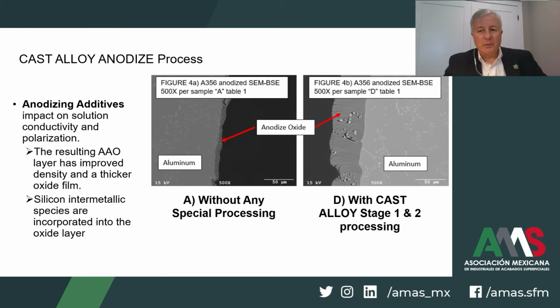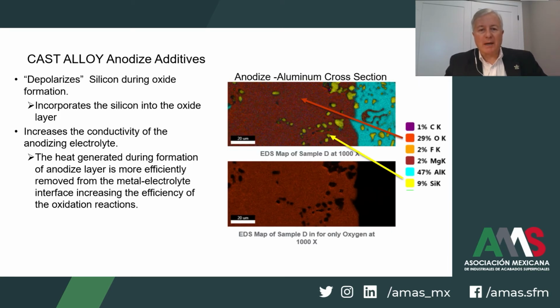In sample D, the resulting oxide layer has improved density while also incorporating the metallic silicon particles into the oxide layer instead of them causing disruptions in the formation of the oxide. As shown here, the additive package to the sulfuric anodizing chemistry acts to depolarize the silicon. Basically, it improves the solution conductivity while helping to remove the heat at the part surface that's generated during the anodizing process. The result seen here in this energy dispersive spectroscopy mapping of the cross-section of the aluminum oxide interface shows how the destabilized silicon intermetallic particles now become incorporated into the oxide layer instead of limiting the formation of the oxide, which would normally occur without using a stage 1 or a stage 2 cast alloy approach.